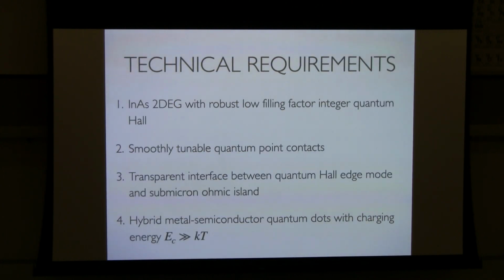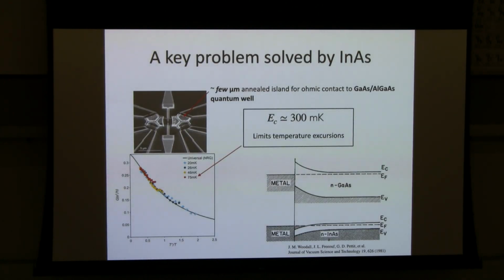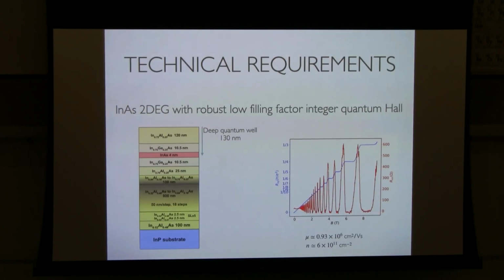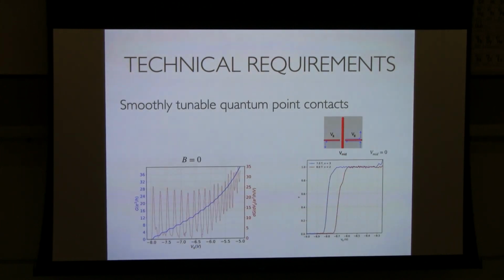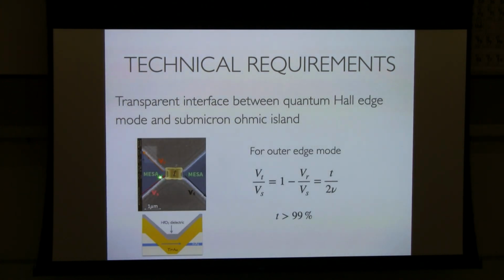And so it turns out that over the last few years, my group has been working on using a different material system to make smaller islands to push up the charging energy, and has been able to see we can get good quantum Hall effect in that system. We can get some really beautiful quantum point contacts that have tunable transmission. We can get tiny metal islands with very good transparency.